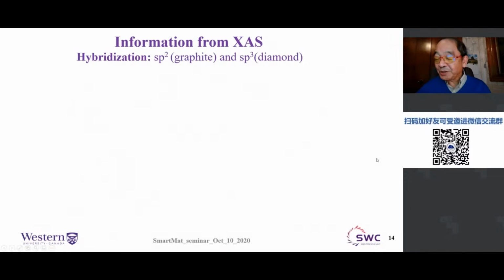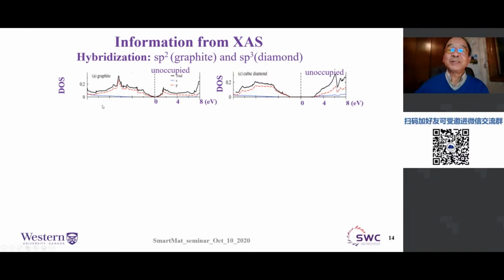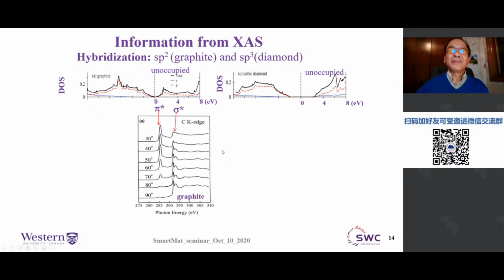Okay. So another piece of information you can get, of course, is hybridization, by looking at graphite and diamond. One approach is to use the density of states, another approach is some local chemistry. So let's start from graphite. Starting from graphite, we can think of benzene having pi star and sigma star transitions. But now graphite is a two-dimensional material. We can actually take advantage of the polarization of the synchrotron. So here is a series of absorption experiments with different angles. So what is this angle?